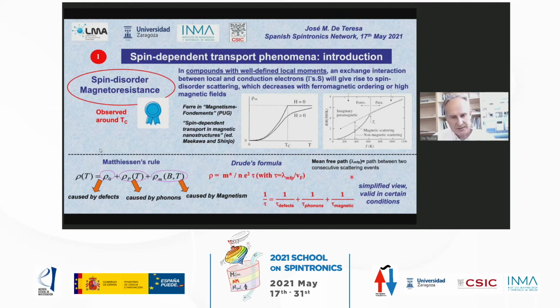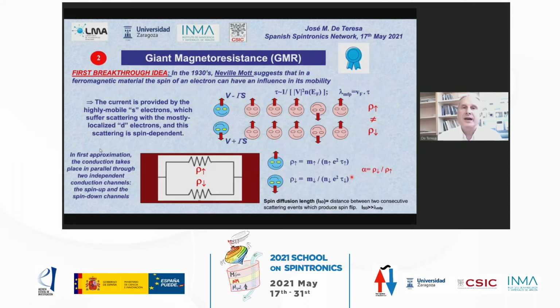This seemed to work for many cases, but then in the 80s, everything changed when a new magnetoresistive effect appeared, which was called the giant magnetoresistance effect. So this is spin-dependent transport, and the first breakthrough idea came in the 30s. It was Neville Mott who suggested that in a ferromagnetic material, the spin of an electron can have an influence on its mobility. So the current is provided by the highly mobile s electrons, which suffer scattering with the mostly localized d electrons. And this scattering can be spin dependent.